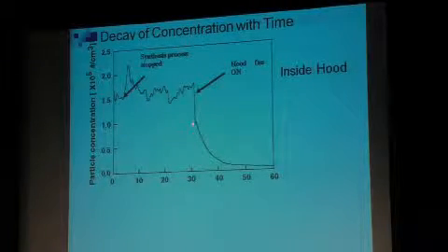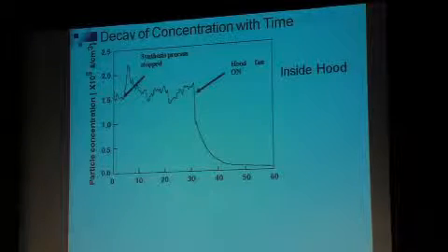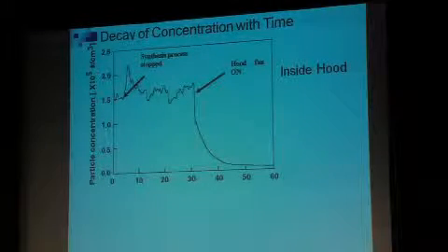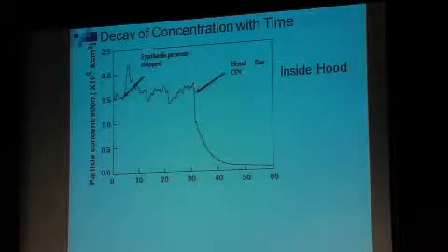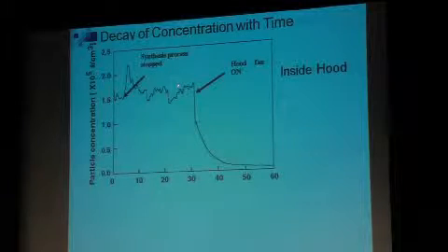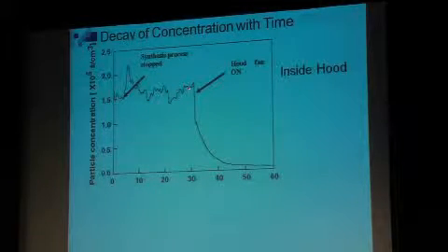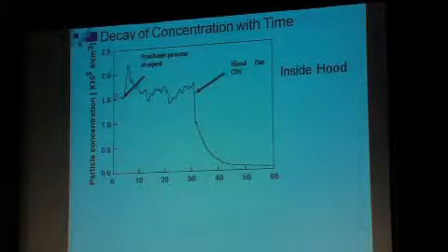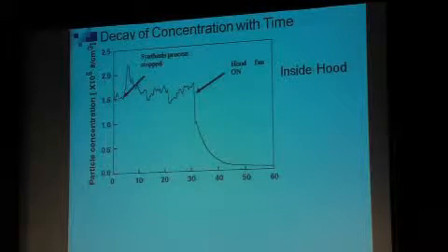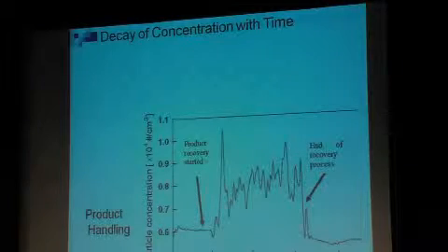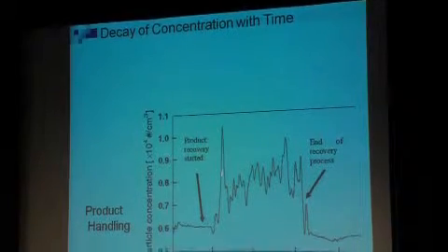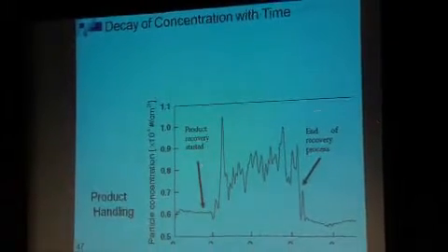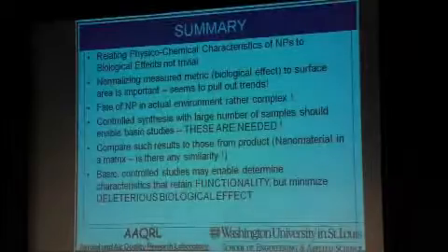When you stop synthesis, there's a certain clearance time. Your graduate students or the worker shouldn't rush in to collect the powder. It takes a long time to clear out, even if the fan is on. Right here, of course, we were producing nanoparticles and the fan was left off. Then it doesn't drop, but if the fan is on, you can see it takes a certain amount of time. So these simple best practices are essential. And when I'm recovering particles, there tends to be a spike. You should do this in the hood with adequate protection and so forth.